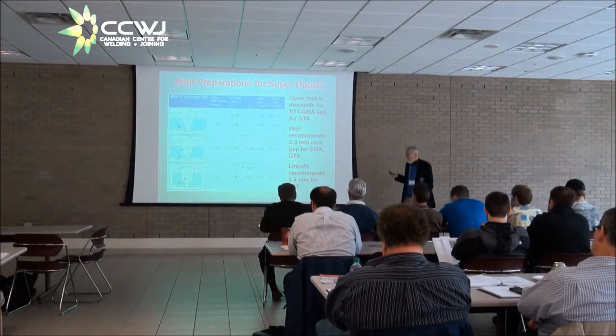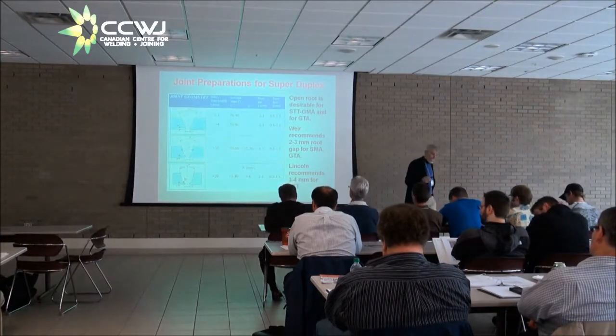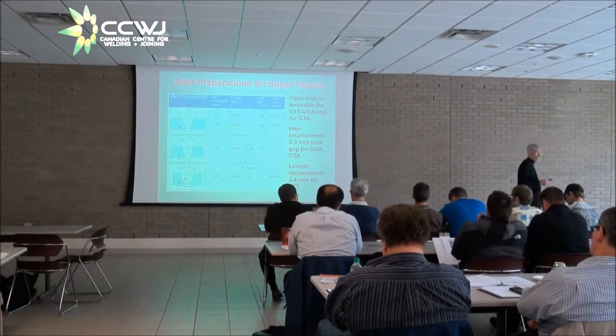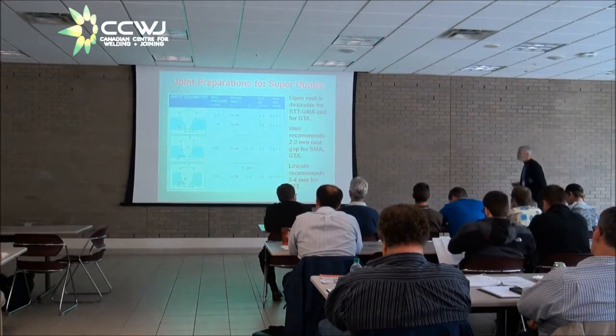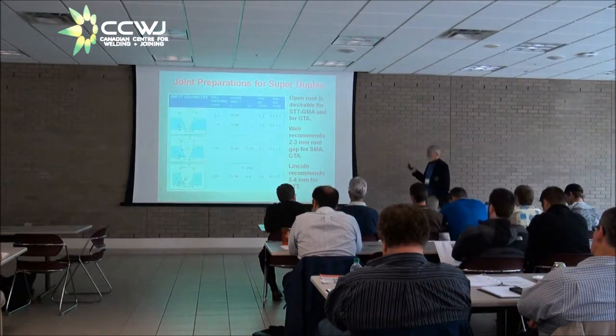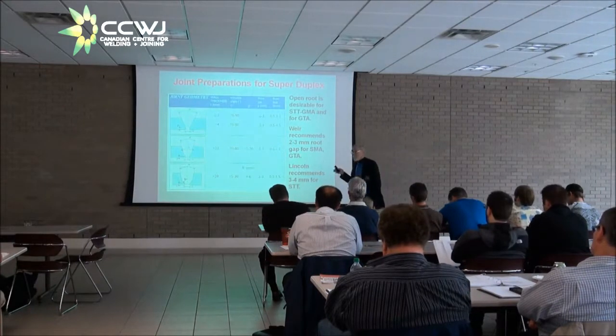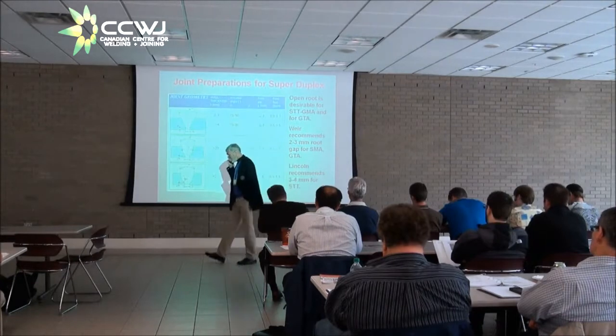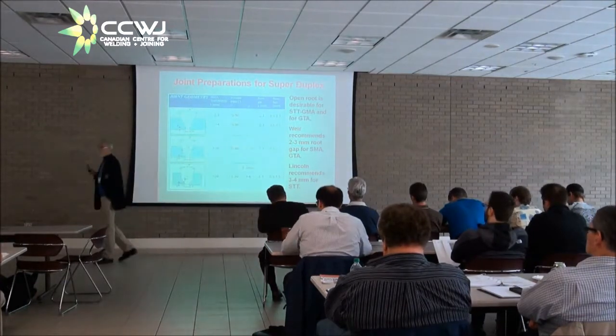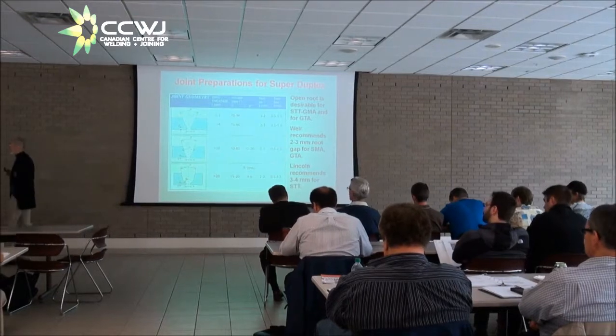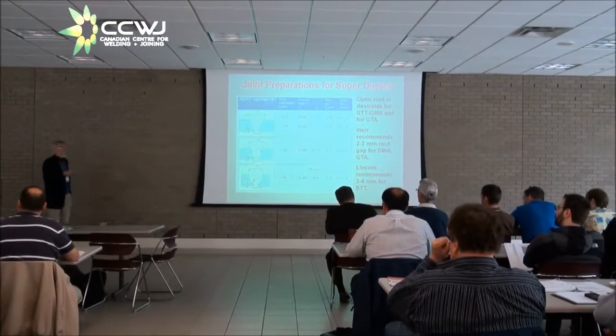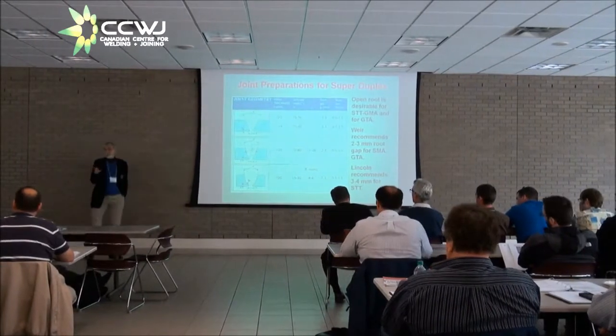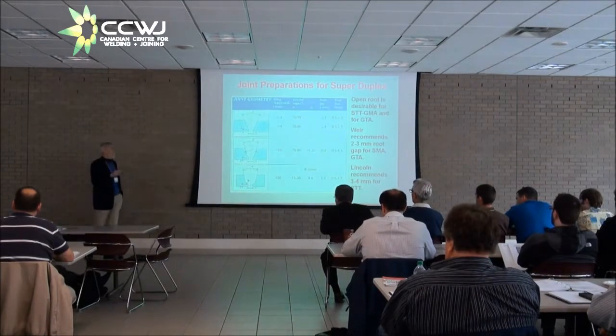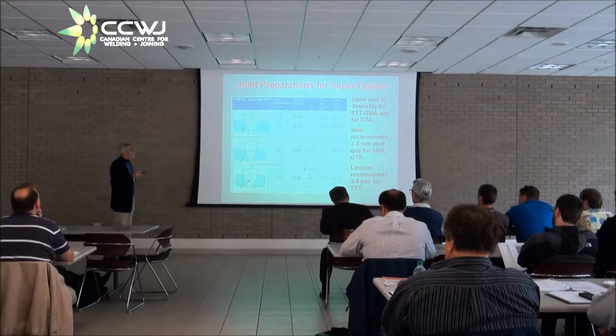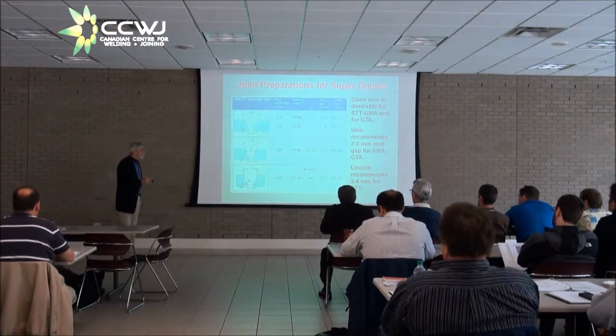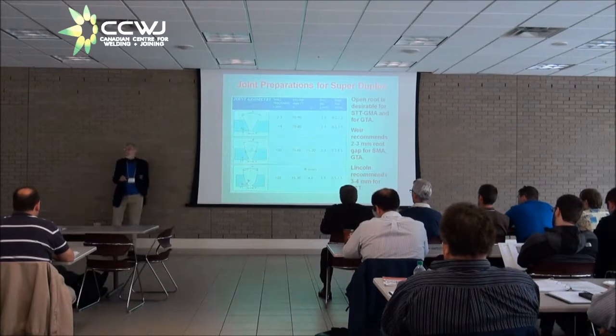Now, it was mentioned this morning that you never want to make an autogenous weld in a duplex stainless because you will have horrible mechanical problems. When you make the root pass in a pipe, you generally do that by gas tungsten arc. And welders don't like open roots. As a matter of fact, they hate it, and they hate you for telling them you have to make a weld in an open root. But the conventional wisdom is you've got to use open roots. And here we're talking about a root gap that might be 2 to 3 millimeters.